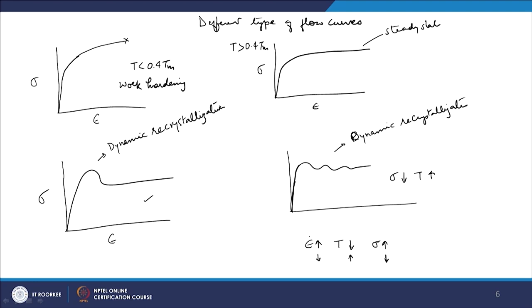In fact a smart thing was done by two scientists, and on their name the parameter is known, and this parameter is called the Zener-Hollomon parameter, which we call Z. This combines both these effects in one. So Z can be written as epsilon dot exponential Q by RT. You can see epsilon dot and T both are now considered here, and sigma can then be shown as some function of Z, where both the effects are combined together and brought in a single equation.